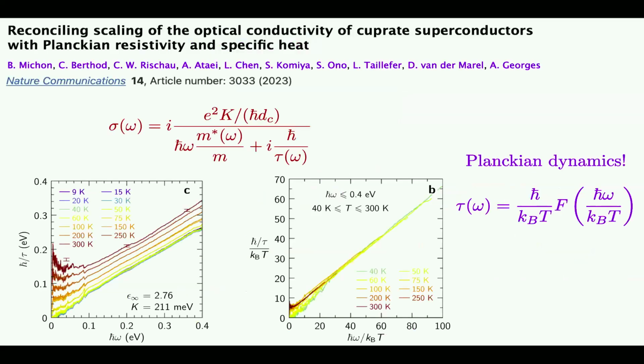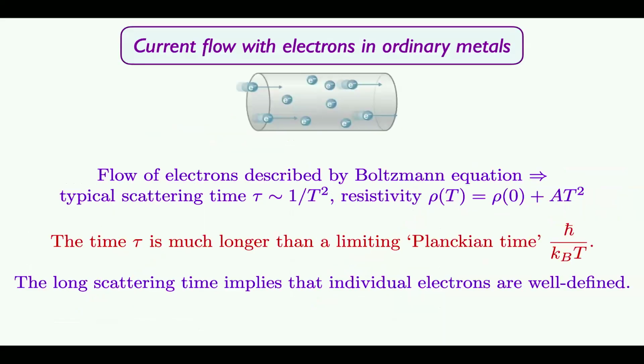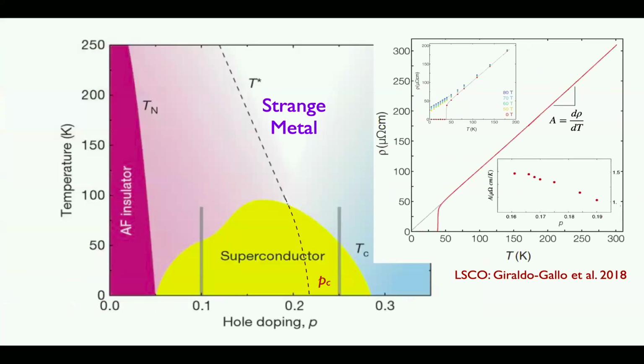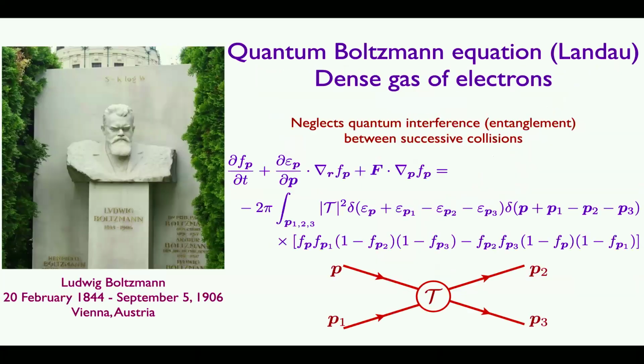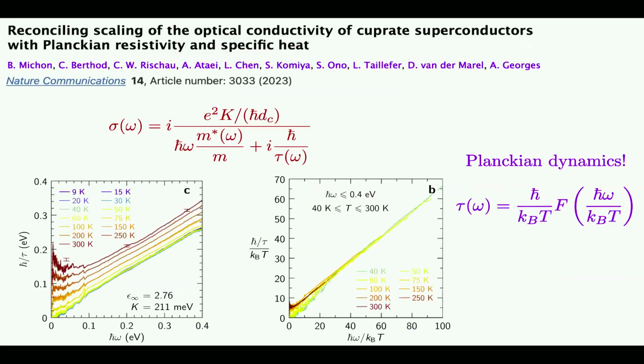So now I come back to the cuprates. I showed you previously this linear temperature resistivity. Now, linear temperature resistivity can come from many reasons, including some very low energy sets of phonons can give you this for not very interesting reasons. But a much more important and subtle property comes in the optical conductivity. So by measuring the reflectivity of one of these materials, you measure the frequency dependent conductivity.